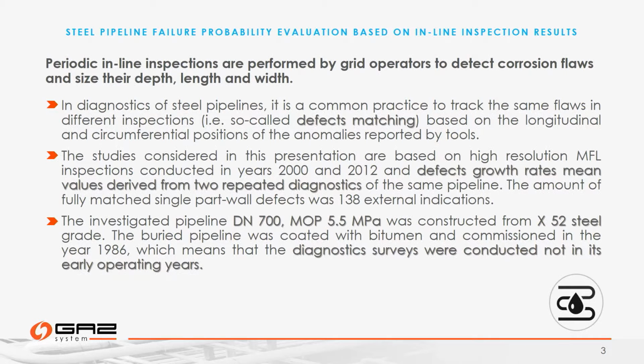Coming back to the diagnostics data, so-called defect matching was employed, which was discussed in detail in the previous paper. We used defect matching for 138 external corrosion defects. It was so-called box matching.